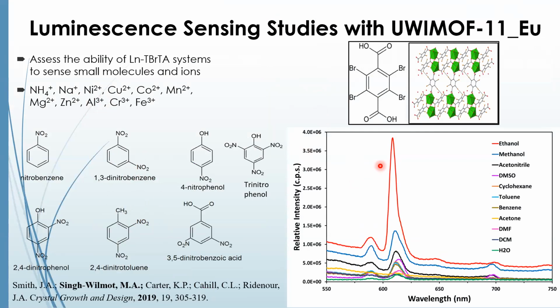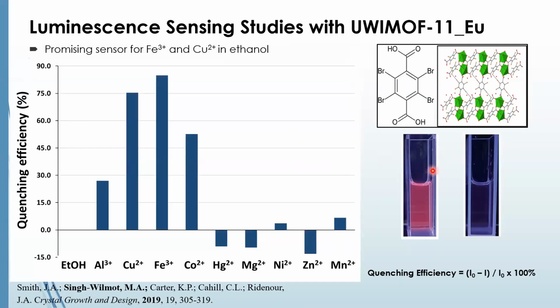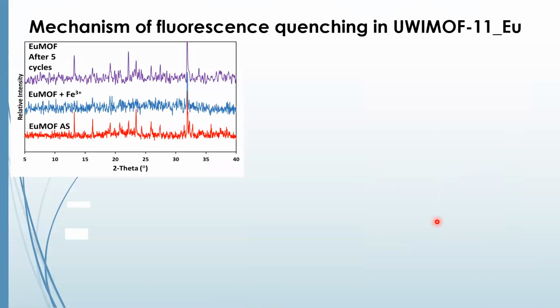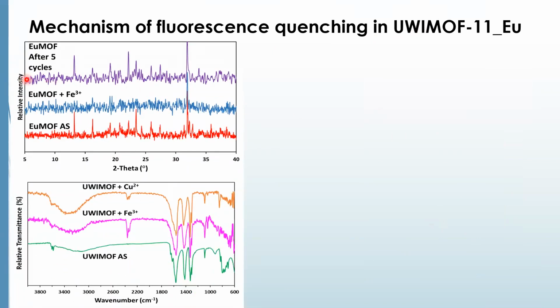So we explored this in all our MOFs, but I'll just show you a couple here because my time is up on me. I should be wrapping up in a few. We explored the sensing properties, and I'll just show you that in the presence of UWIMOF-11, we're sensing iron and copper. In fact, you see the quenching efficiency is great in the presence of iron and copper. So here we have some pictures showing you we have red emission, and once iron or copper is present, the emission is quenched. And we did quite a bit of studies on exploring the mechanism of quenching and improving that, so we can reuse this as a sensor for over 5 cycles.